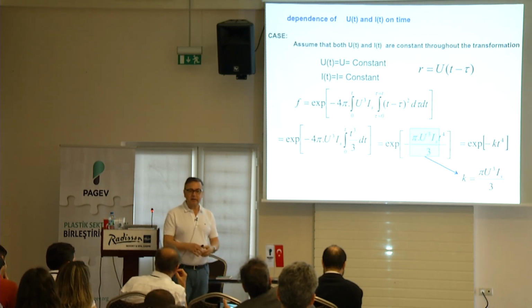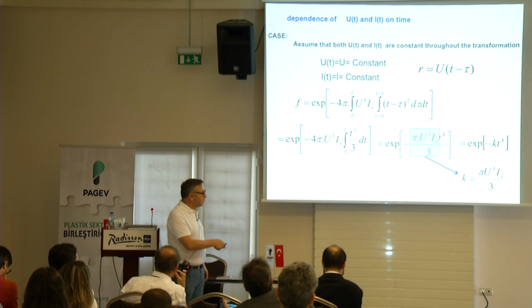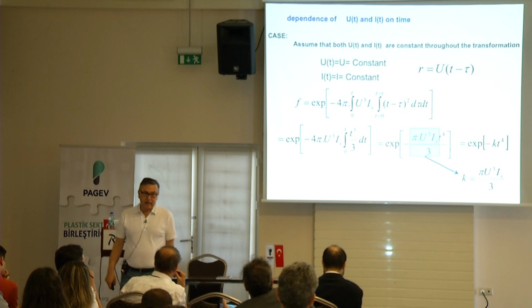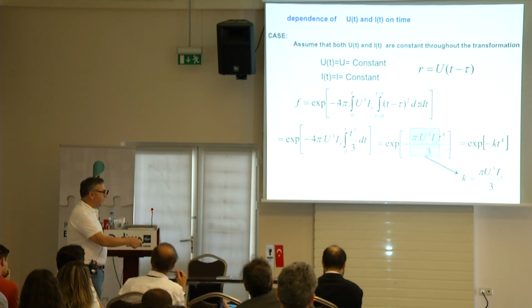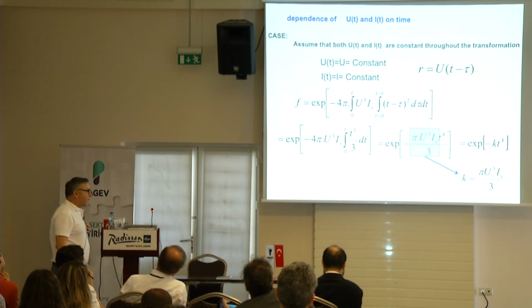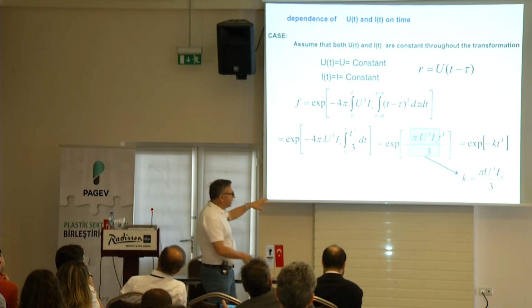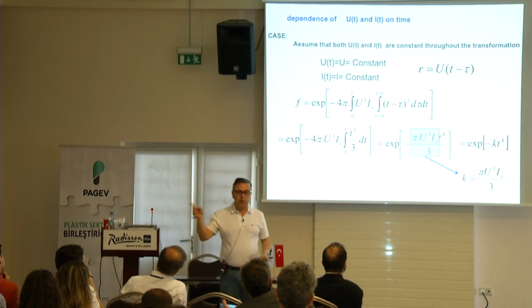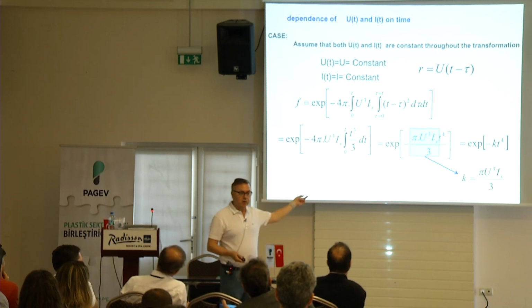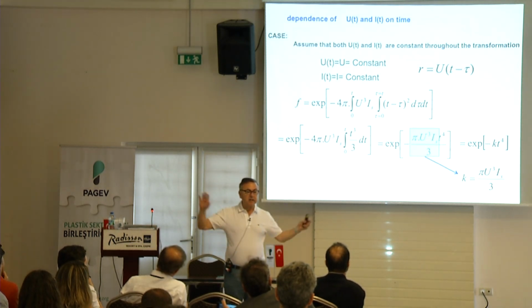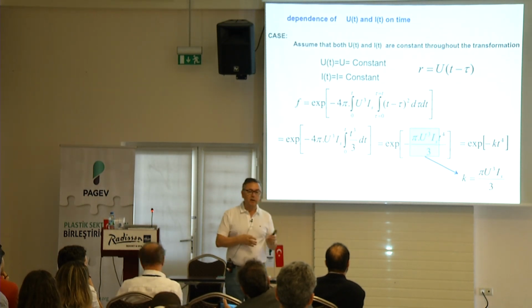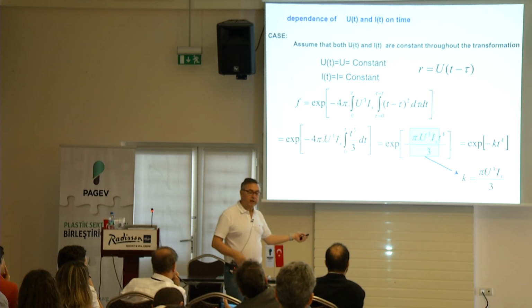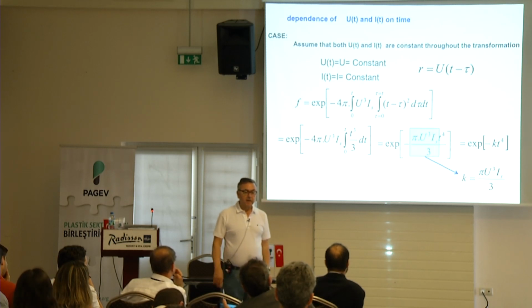What do we do industrially? We never control the growth rate. We control the nucleation rate. It's not that easy to do even though it's significantly powerful. But you can easily see, since the molecular weight controls the viscosity, which controls the growth rate, what happens when you change the molecular weight. You go to a low molecular weight material, what's going to happen to the rate constant? Crystallization growth dramatically increases.